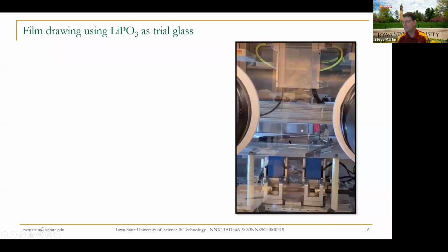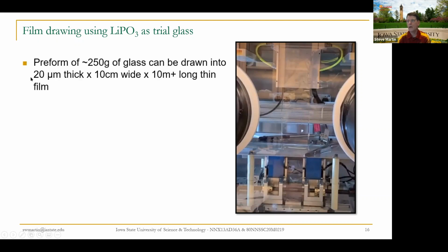Now it's really hard to see because glass at 20 microns is pretty transparent. But if you look real carefully, that's one edge of the film, and that's another edge of the film, and then the glass is between that. We just pull it out, and we get rolls and rolls of thin film, about 20 microns thick. We get about 10 centimeters wide. We get these 10 meter plus preforms.